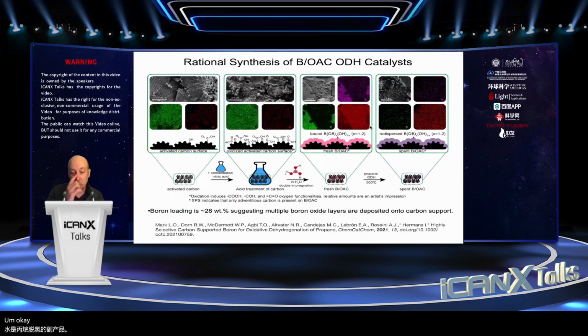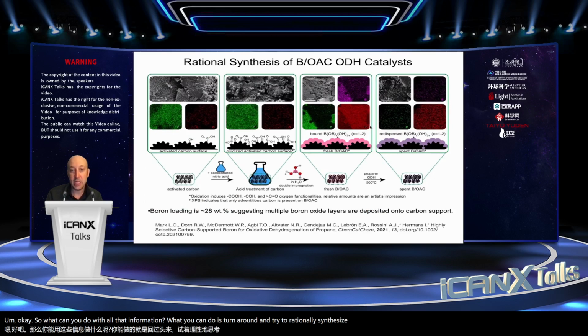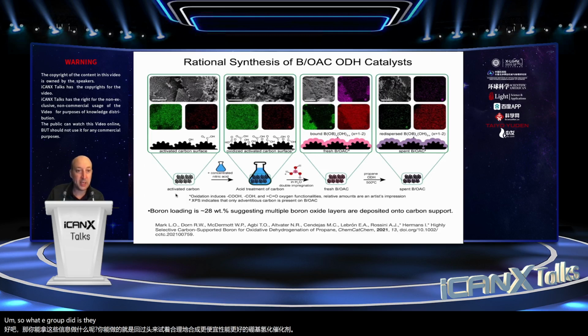Okay, so what can you do with all that information? What you can do is turn around and try to rationally synthesize cheaper and better performing boron-based dehydrogenation catalysts. So what Eve's group did is they took activated carbon. You can treat this with nitric acid. This will introduce oxide functionalities, carboxylic acids, ketones on the surface.